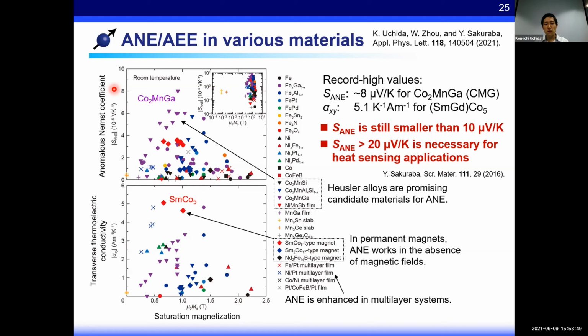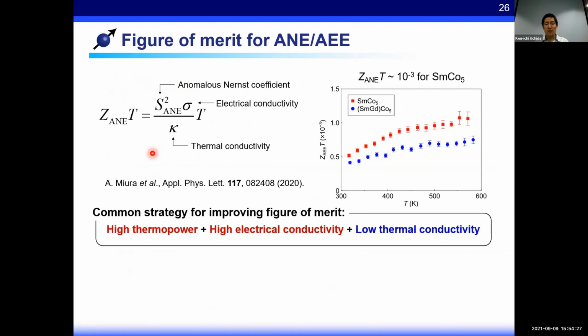But recently, sometimes the experimental results clearly deviate from the first principles calculation. And this means that other factors should contribute to the anomalous Nernst effect. Of course, in a similar manner to the spin Hall effect, the extrinsic contribution coming from the impurities should also be important in the anomalous Nernst effect. In this sense, there is no clear experimental guideline to further improve the anomalous Nernst coefficient. So yeah, actually the systematic investigation is important.